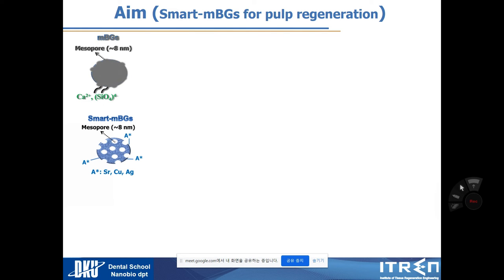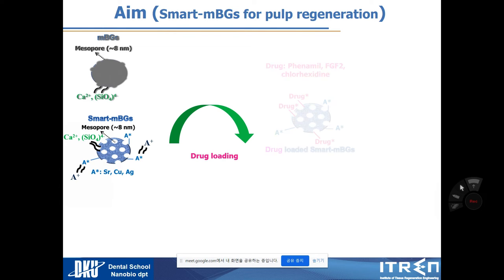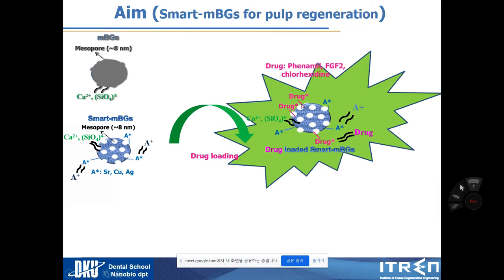My aim of this study is to make a smart mesoporous bioactive glass for pulp regeneration. Originally, many people have made this mesoporous bioactive glass nanoparticle, but today I want to accelerate this potential. So I want to dope it. Doping means adding strontium, copper, or silver ions to this bioactive glass. Then they can release calcium and silicate as well as our doped, loaded ions, and these doped ions can have very special biofunctionality. If I additionally add a drug using these mesopores, I can load and release the drug as I want. And when these nanoparticles are taken up by odontoblasts or pulp stem cells, they differentiate into odontoblasts, which means dentin tissue.